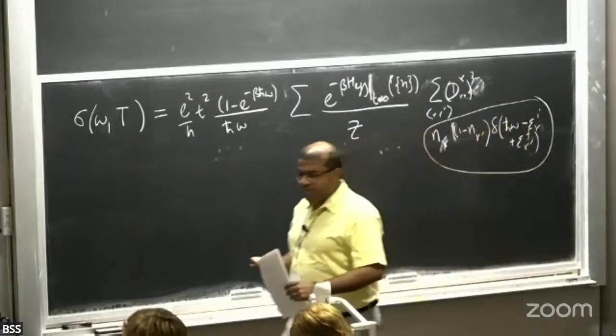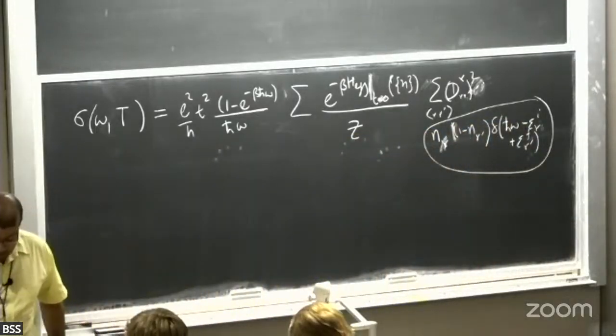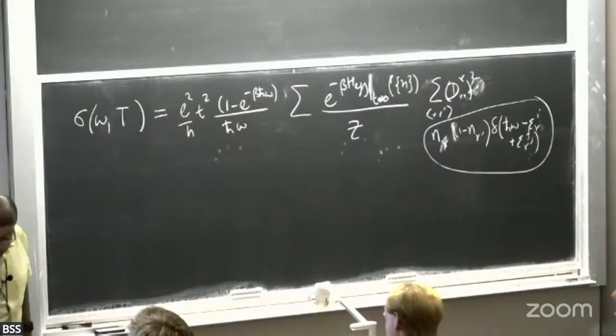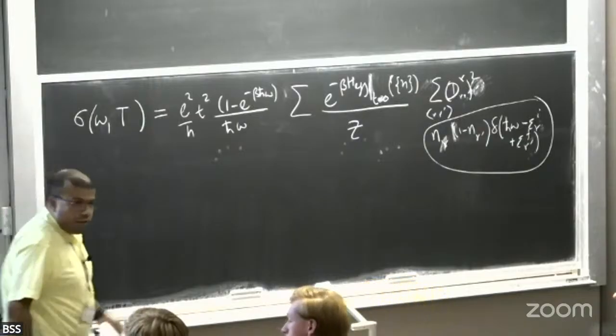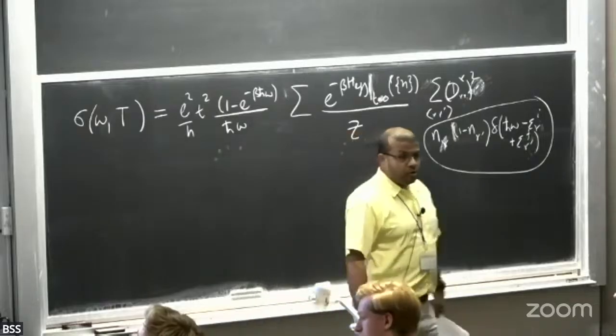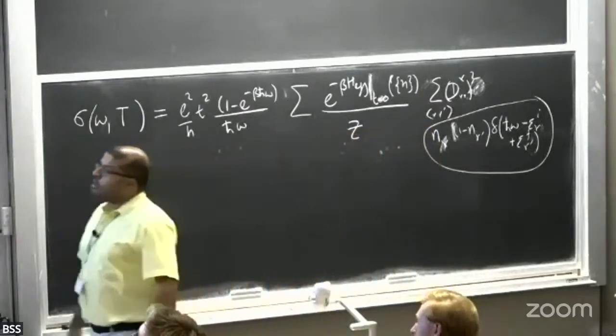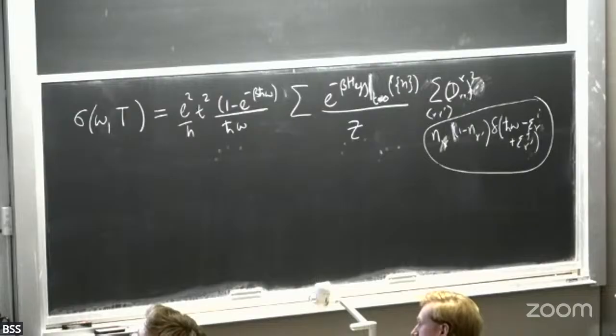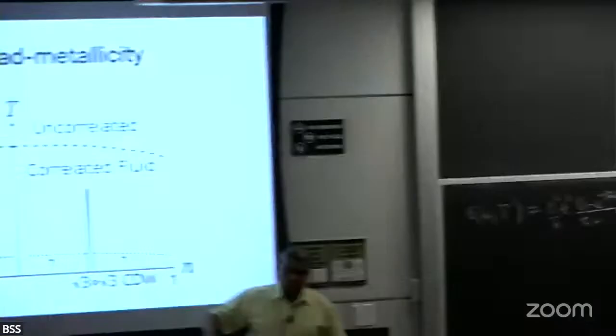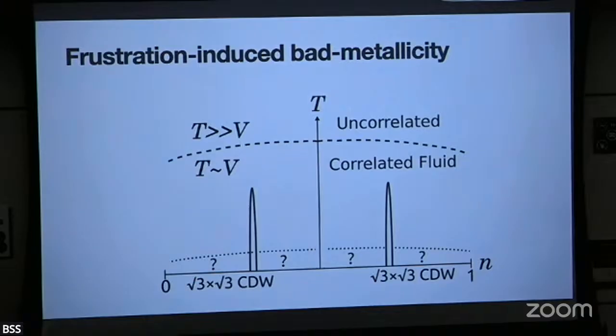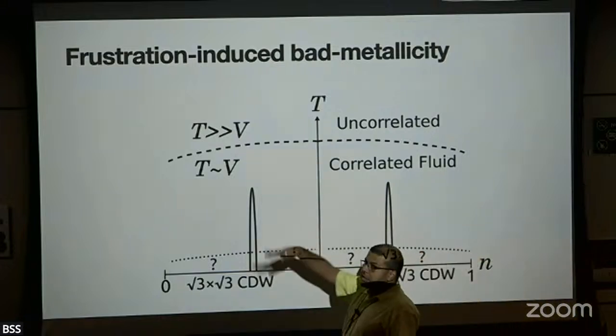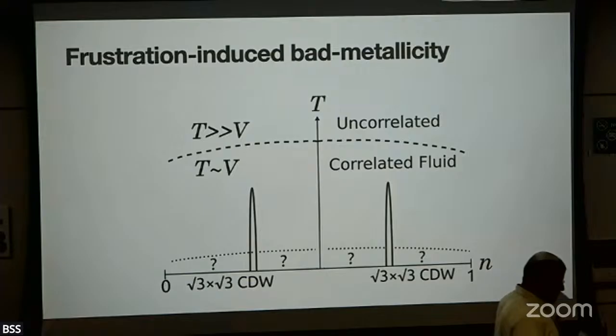Okay, so this seems somewhat interesting, not the usual kind of transport regime, and we can do this. Now, before I show you what the actual data looks like, this is what you expect the system to do. If you're at temperatures, again, V is much larger than T, the hopping. If you're at temperatures much above V, then it's some uncorrelated classical gas. When you cross over through the scale where temperature is of the order of V, this is where the electrons really start feeling the effects of the correlations. You're going into some correlated fluid.